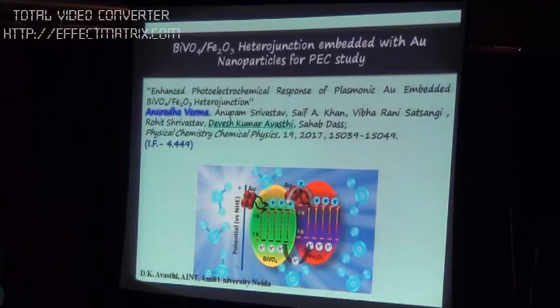Okay, so we tried the same thing with other materials. Instead of putting layers, we embedded gold nanoparticles inside bismuth vanadate and iron oxide. And this material we utilized, again, for photoelectrochemical splitting of water. Then again we got an increase in hydrogen production. So these were very interesting, that by introducing just gold nanoparticles, we are improving the existing efficiency of semiconductors.